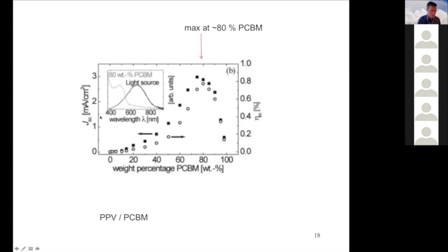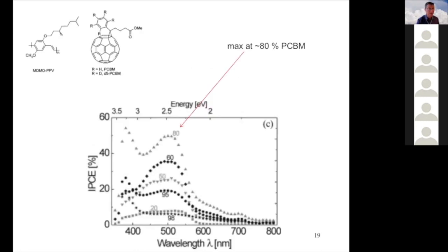And you also see it here at the other side. Also the incident photon to current efficiency also shows a clear maximum at 80%. And it tells you something about how efficiently the photons falling on the system are converted into electrons. For this particular combination of polymer and fullerene, 80% clearly is the maximum. And we also see that in this graph where you see the efficiency versus wavelength. So you see you go from 20, 50, 60 at 80%.